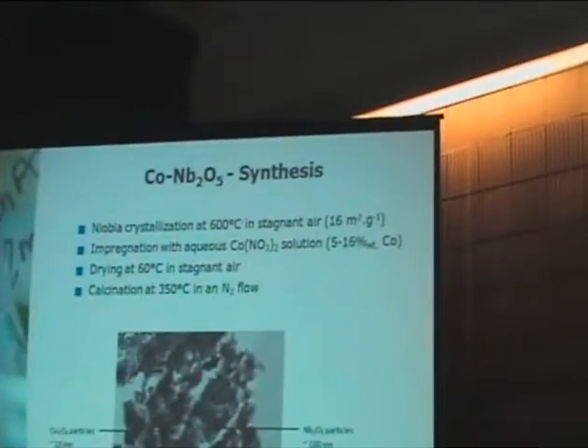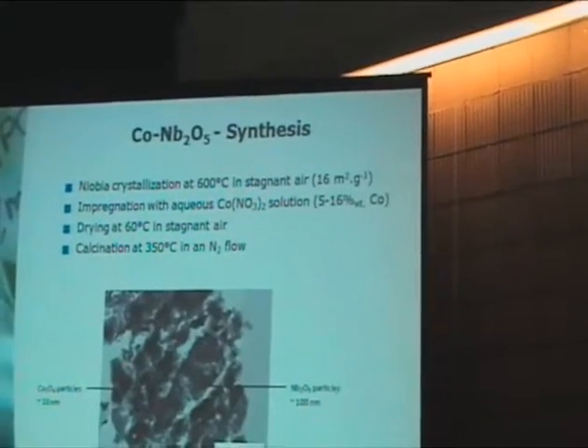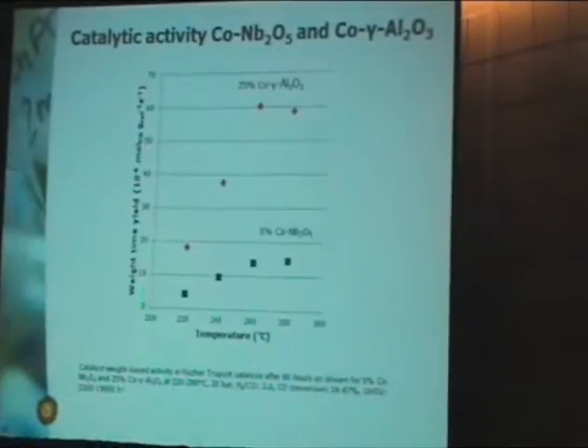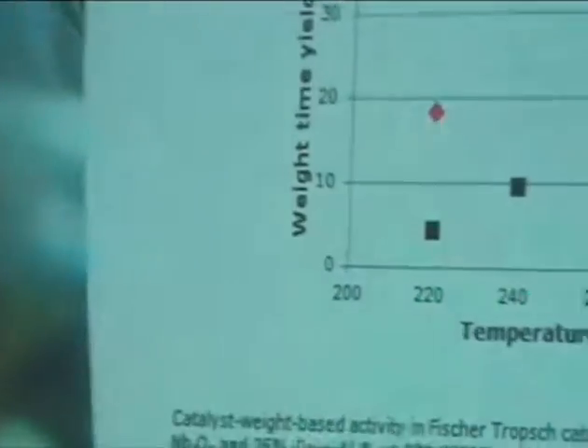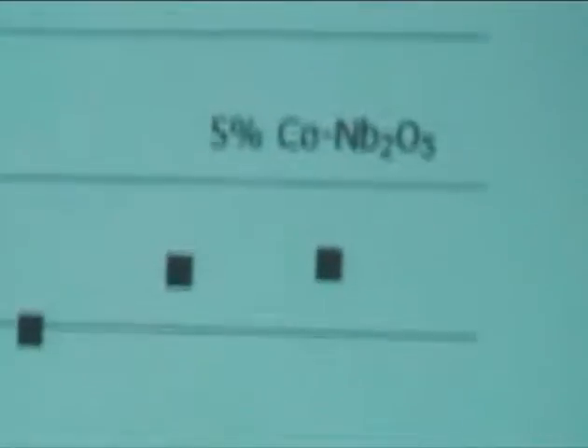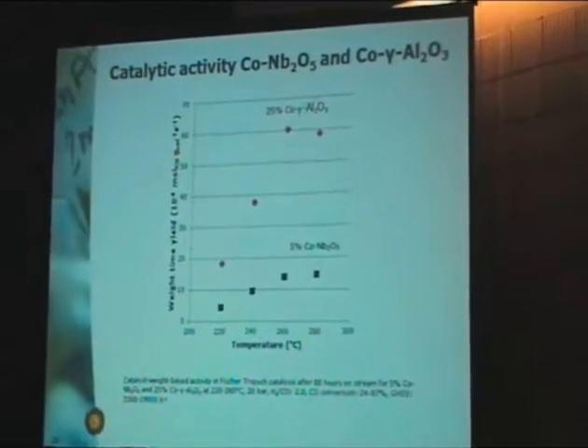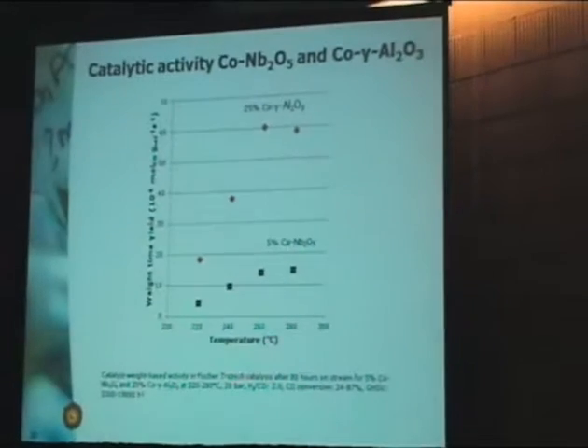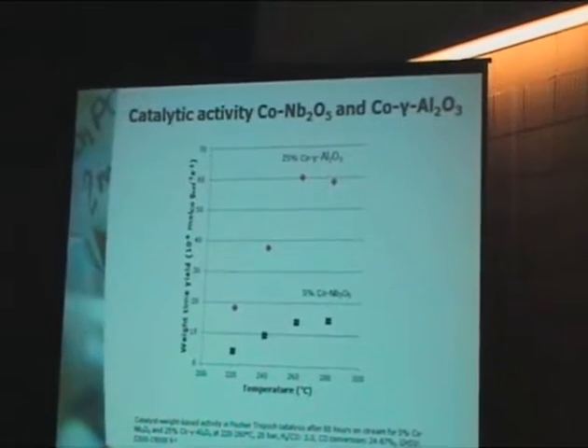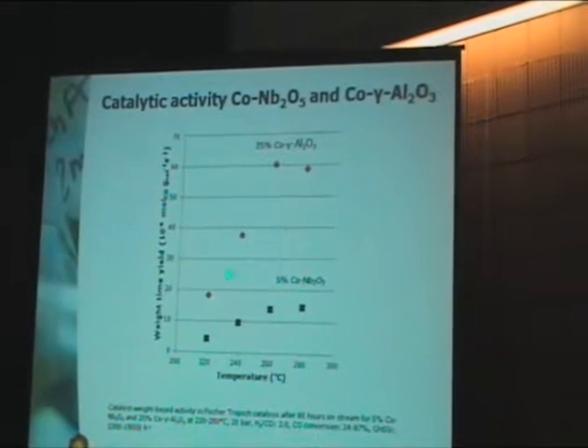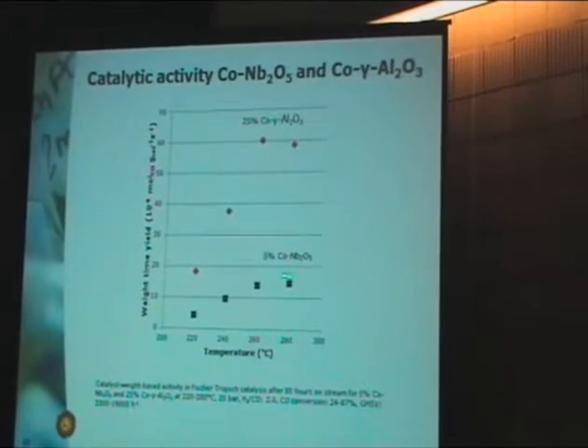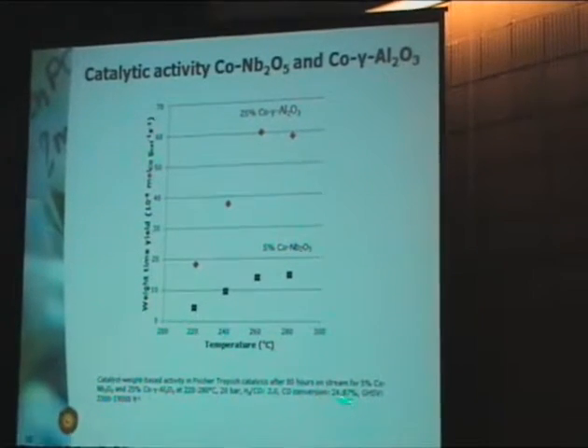So we chose to go for 5 weight percent cobalt to prevent this agglomeration of the cobalt nanoparticles. If we then plot the weight time yield, so per gram of catalyst, as a function of temperature, the cobalt niobium with 5% cobalt, of course, has no chance to compete with 25 weight percent of cobalt on gamma alumina, the classical gamma alumina supported cobalt catalysts that have been studied so much also by Burtron Davis and his group. The activity is way higher. There's a plateau because of the very high CO conversion that we achieve at the highest temperatures.